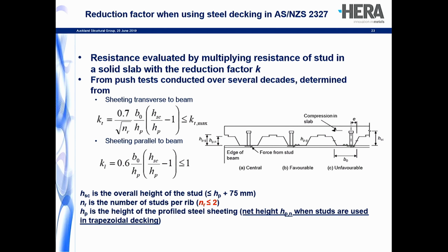So I guess the main things you can see from here is that the important things are the number of studs within the rib, the width of the rib, which is given the denotation B0, the height of the profiled steel sheeting, and the height of the stud HSC. And it's very important that you have a sufficient projection of the stud above the sheeting height HB. So one of the things to watch here is that in some of the older standards there was no limitation on the number of studs that you could weld within a rib of a profiled steel sheet. In Eurocode, as well as 2327 now, it's limited to 2. You can put more in, but you won't get any more capacity out of them.